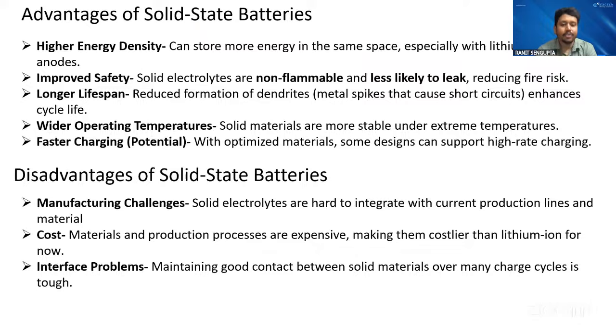Now, what are the advantages and disadvantages of this type of battery? The advantage, obviously with the most impact, is higher energy density. In the NMC cell we are getting an energy density of around a maximum of 250 watt hour per kilogram. By using solid state batteries, we can get 25 to 30% more energy density on the NMC itself. Suppose we are using LFP, we can reduce the weight by 25 to 30%. So we can reduce the weight as well as the overall area, and get 25 to 30% more range on the same area or the same weight.